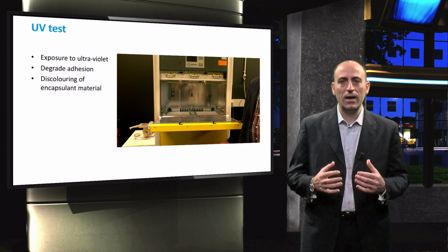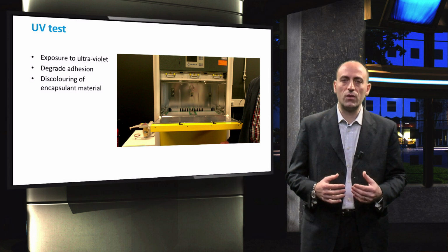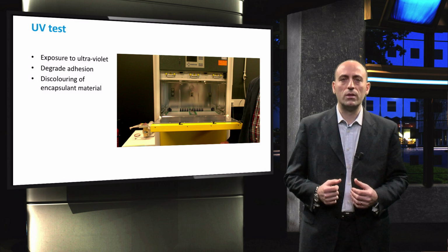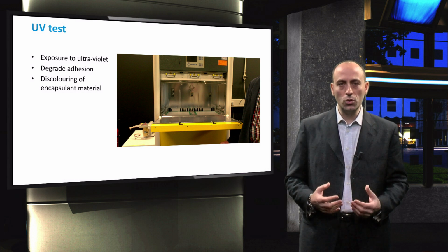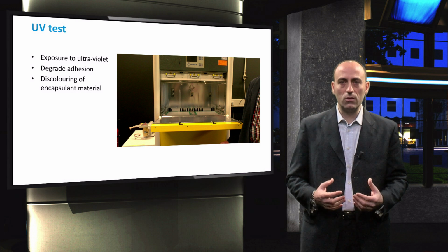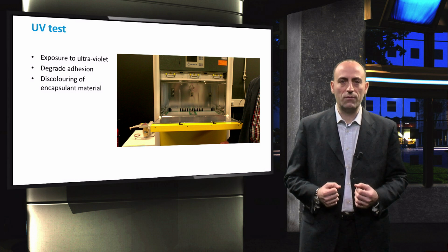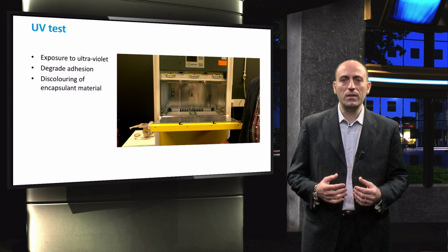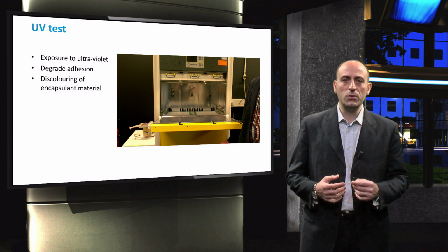Although the IEC 61215 prescribes the UV test, it is criticized that the total exposure is low compared to the exposure a module experiences outdoors in a 25 years lifetime. In the following video, we will see an example of a PID and a UV test machine as used at ECN.